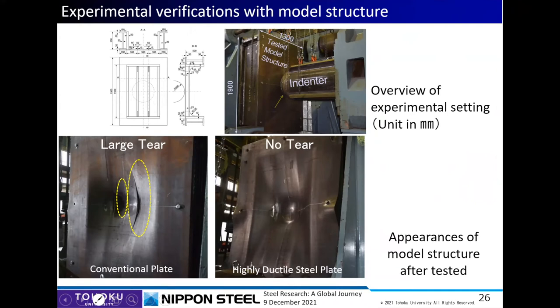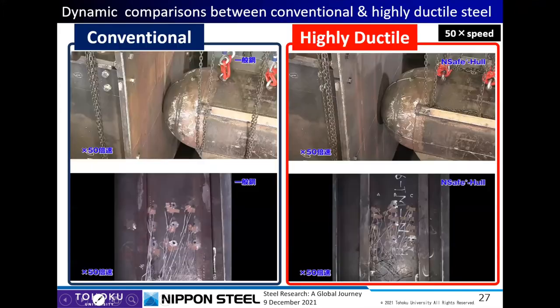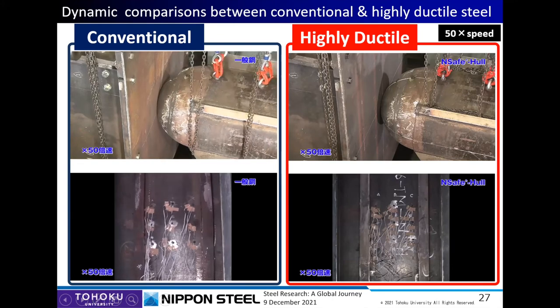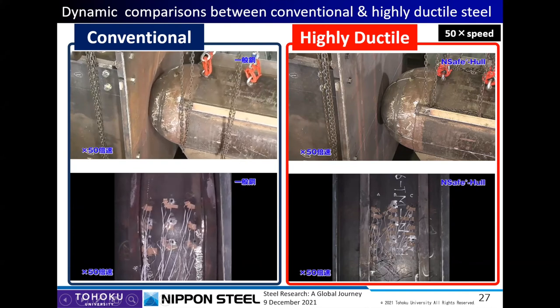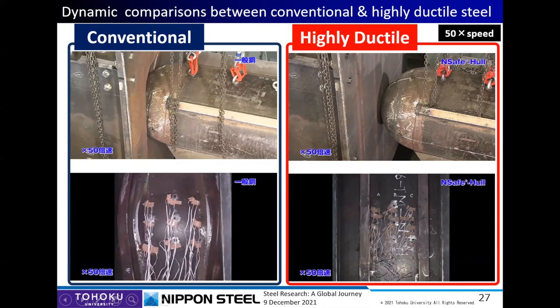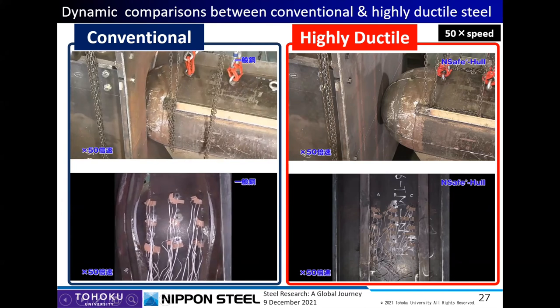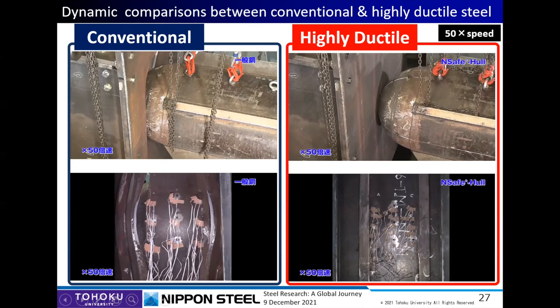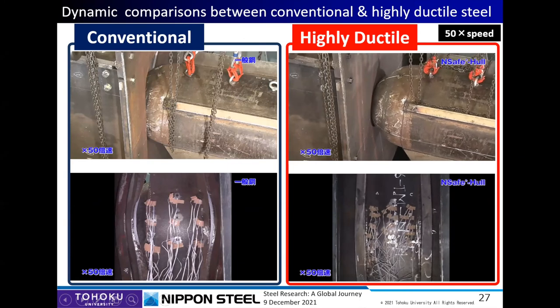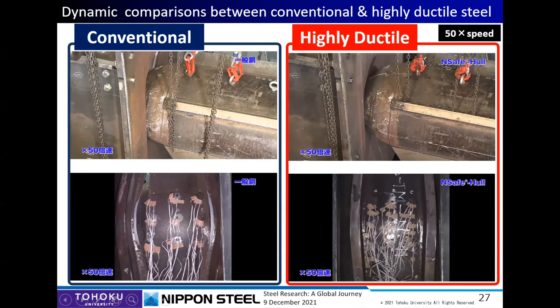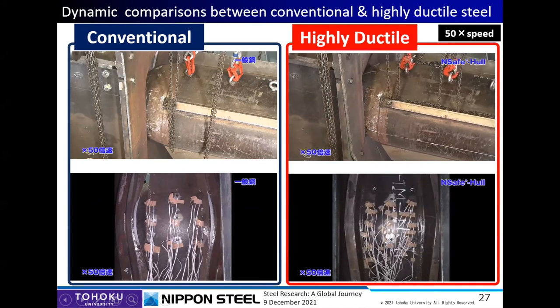Let me show you movies of the testing. This is a conventional steel plate. The indenter is moving this way. And finally, you can see a large tear along the weld line here, and you can see a crack here. But in this highly ductile steel case, we can see large deformation here, but we cannot see any large opening of tear on the surface.